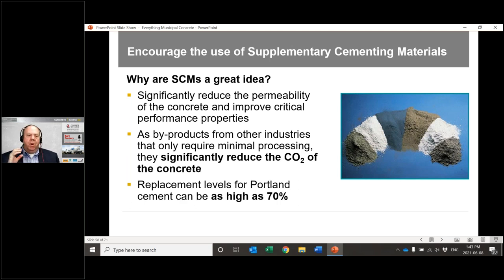But if we went back to that one slide, which I should have never showed you, which was mixed proportions, the impact of slag from a CO2 standpoint is negligible. So the more SCM that we can put into the mix, the lower the carbon footprint of the concrete itself.